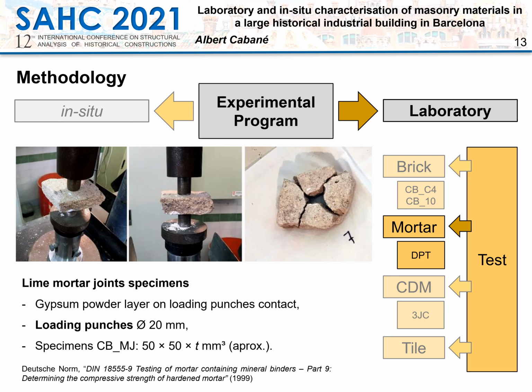For the case of the mortar samples, it was difficult to prepare regular specimens with square dimension of 50 mm side as the German standard recommends. This difficulty arises from the low consistency and cohesion of the samples.